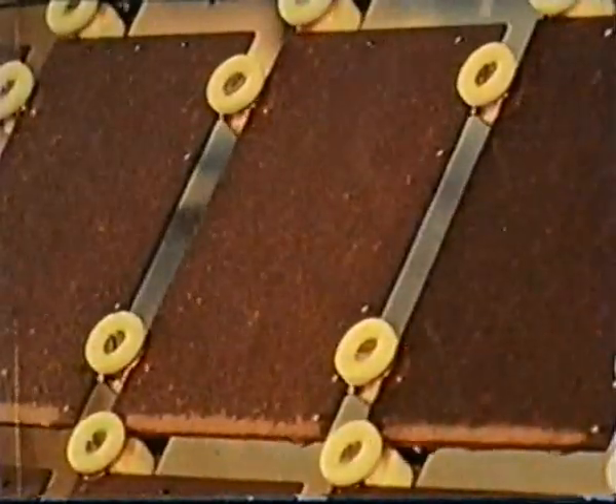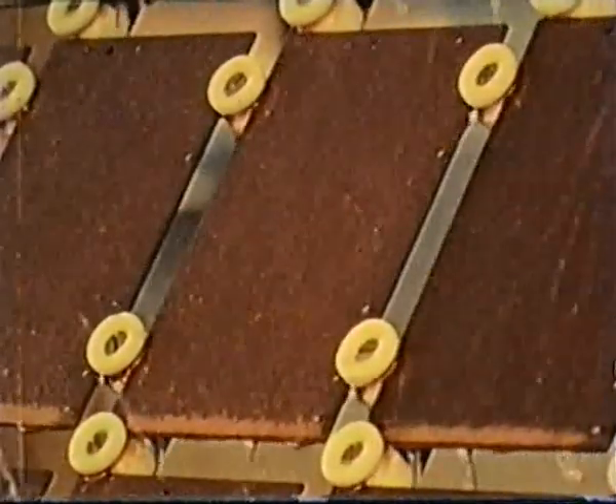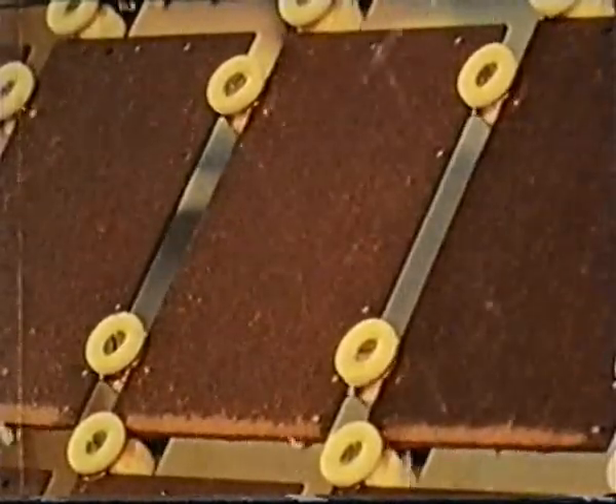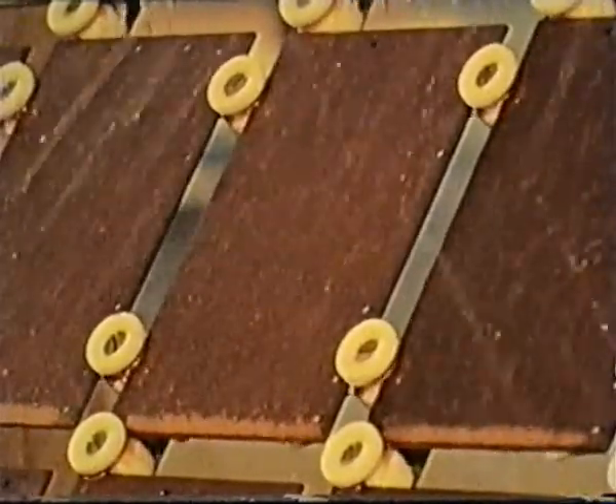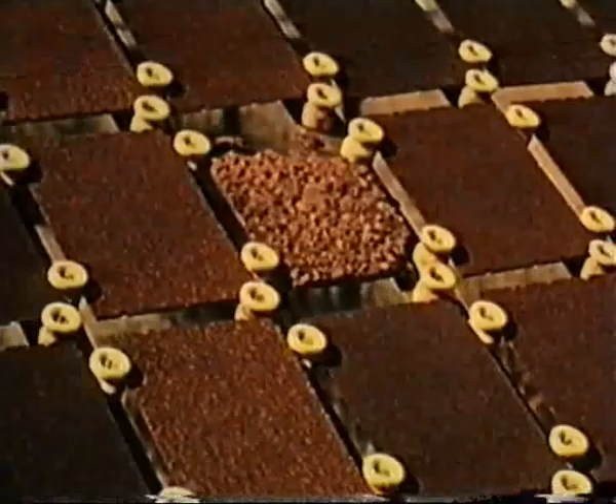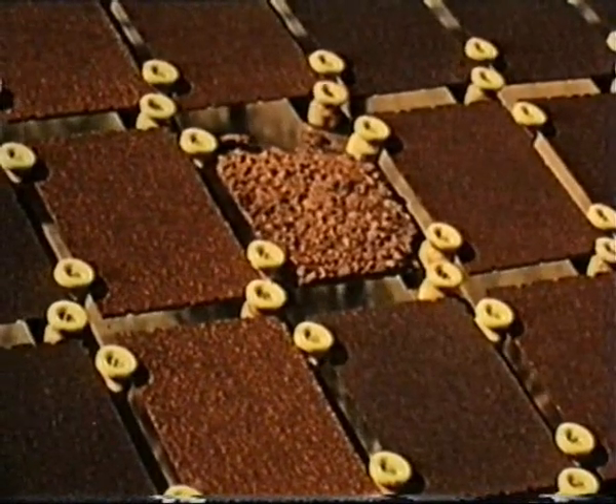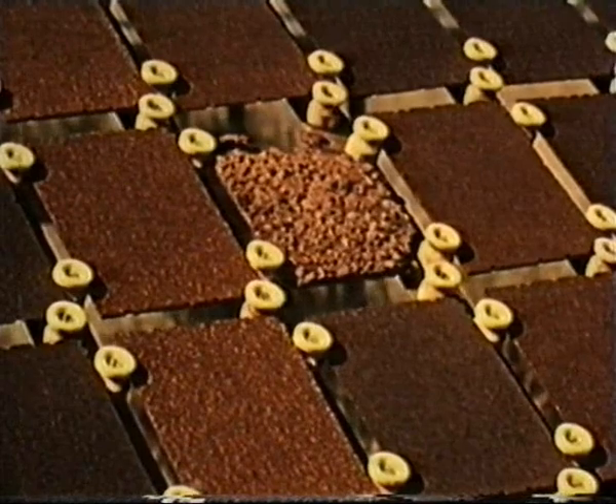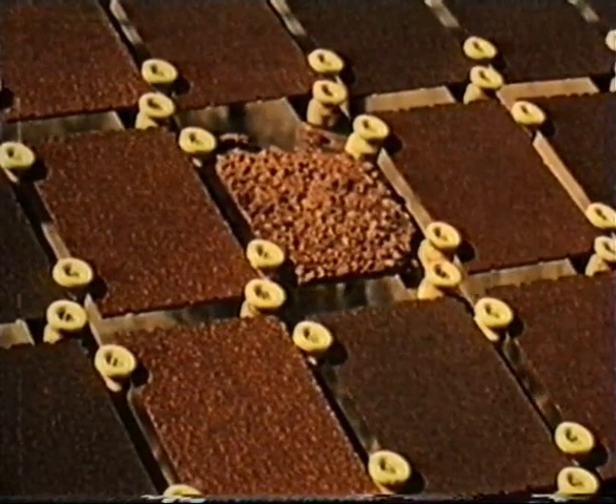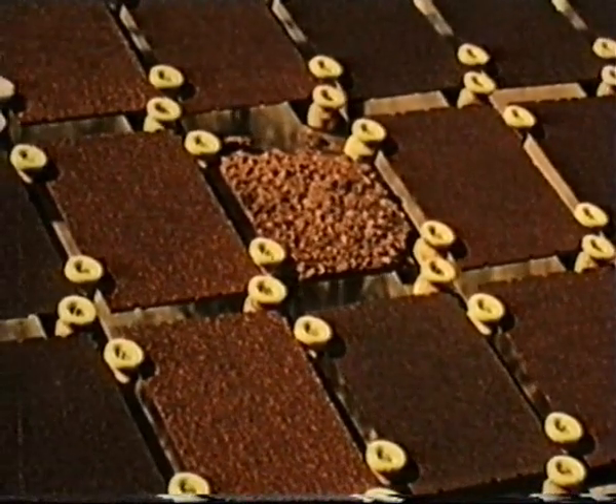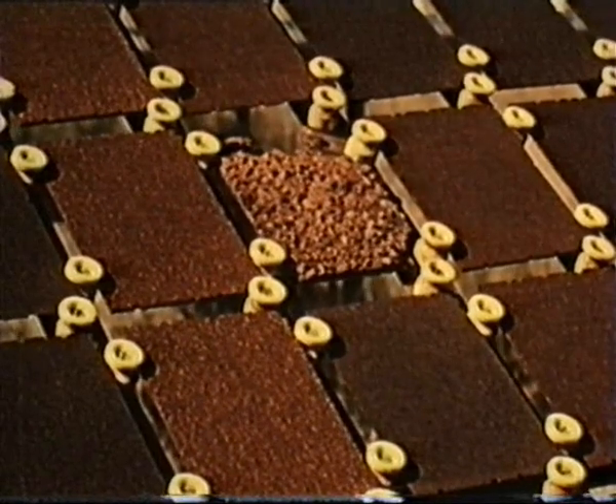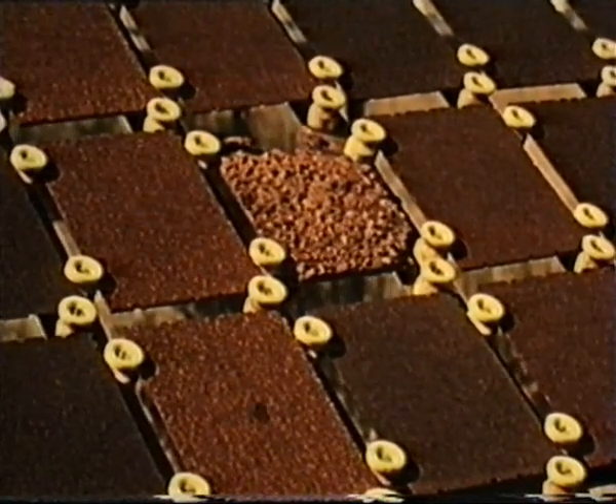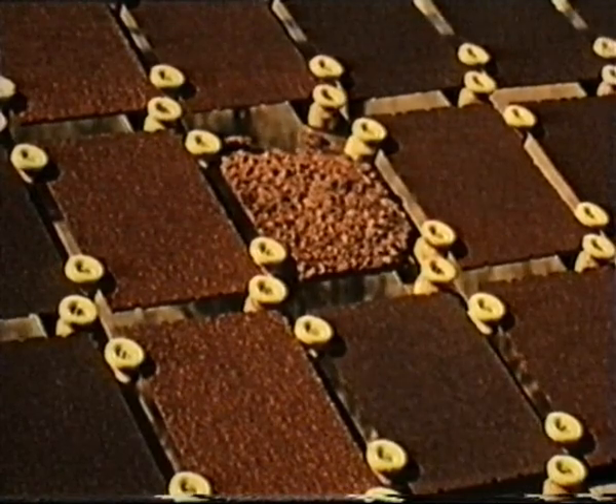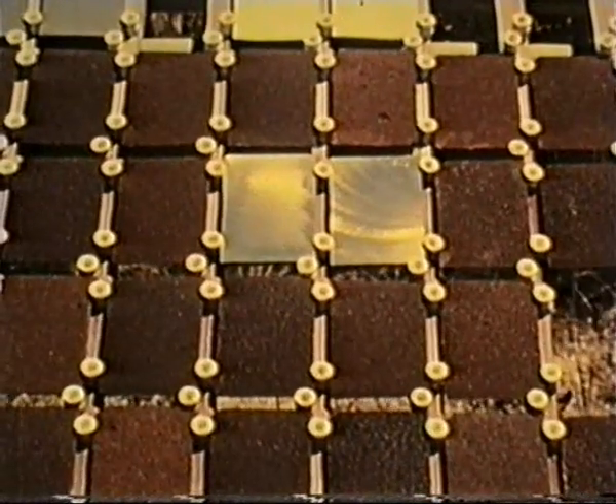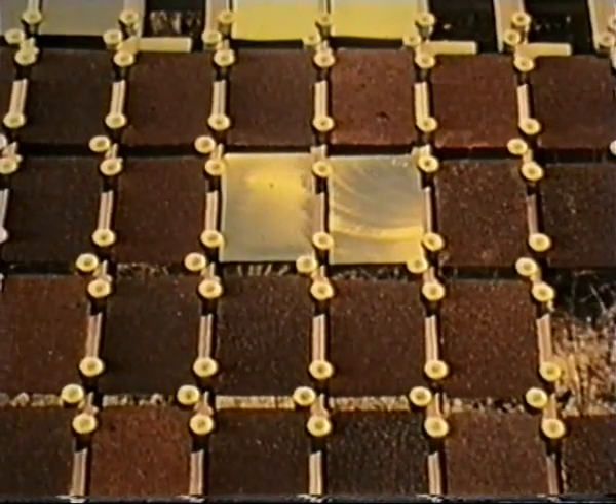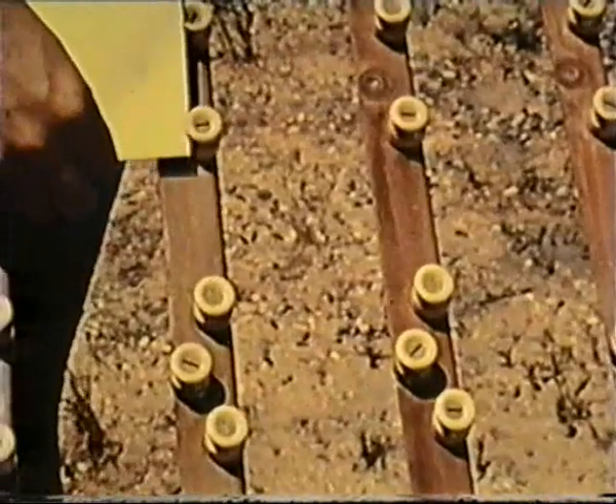Rust is a product of destructive action, but it may also have a protective value, although the mechanism of that protection is different from that of the passive films on stainless steel. Steels that show poor resistance to corrosion form heavy voluminous rusts that offer little resistance to the penetration of moisture, as in the case of this specimen exposed only 2 years at the Inco corrosion testing facility at Kure Beach, North Carolina. Differences in the rate of progress of corrosion are illustrated by the behavior of 3 steels.